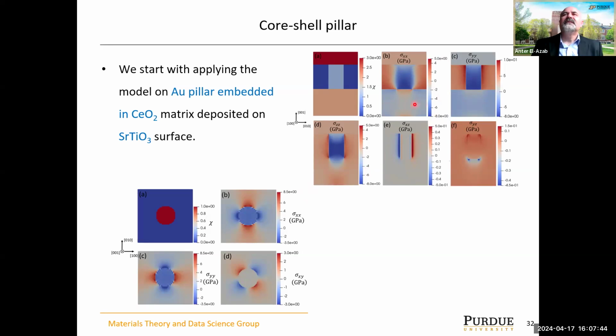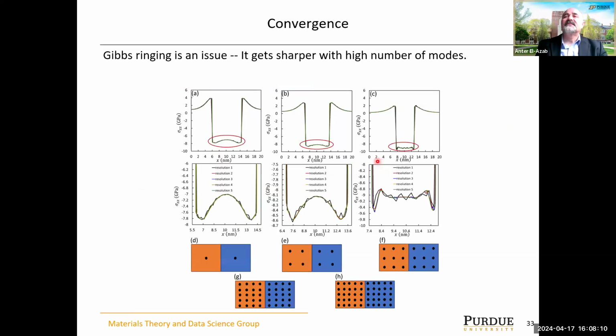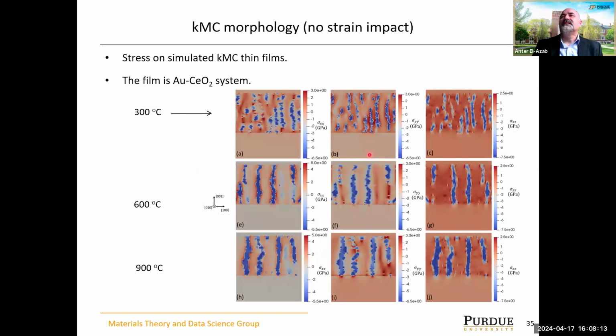Eventually we have it. And what you see here is just a sample stress calculations over a cross-section of the film, a vertical cross-section here, and a horizontal cross-section here. They test nicely with known solutions in the literature for this idealized cylindrical pillar in a matrix. And we take this to solve the more complex problem of having these irregular shaped pillars now in the matrix. And we were able to capture the strains in a very nice form.